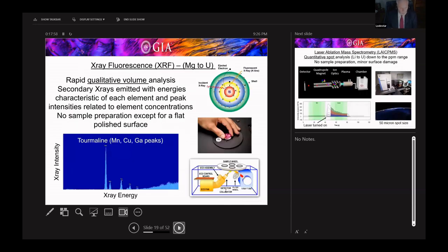There are two real techniques that we use for chemistry analysis. The first is called X-ray fluorescence, or XRF. It's a rapid qualitative volume analysis. You have a beam of incident X-rays from the instrument that eject electrons out of the atoms. And then you get a higher level electron dropping down and emitting X-rays as fluorescence. And those X-rays are characteristic of the chemical elements in the material.